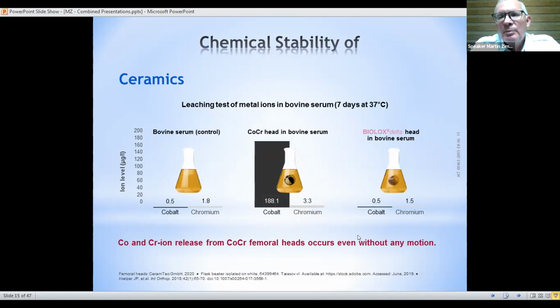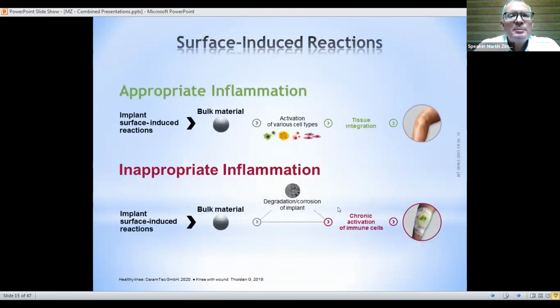Some may ask the question, how is it possible to measure the release of chrome or cobalt ions from the ceramic? We have done that because many years ago there were claims that, due to the fact that you have chrome oxide in the ceramic to enhance the mechanical characteristics, this chrome oxide may be released out of the Biolox Delta and create metallic particles. To demonstrate that, we did testing with bovine serum as a control, with cobalt chrome ball heads and ceramic ball heads, both the same size, without any motion, stayed for 7 days at 37 degrees. As you can see here, with a cobalt chrome ball head we have a release of cobalt as well as chromium particles, ions in the fluid, which was not the case with the ceramic. So I think we finally demonstrate that there is absolutely no risk of any release of metallic ions from the ceramic ball heads. Let me speak now about the bulk material.